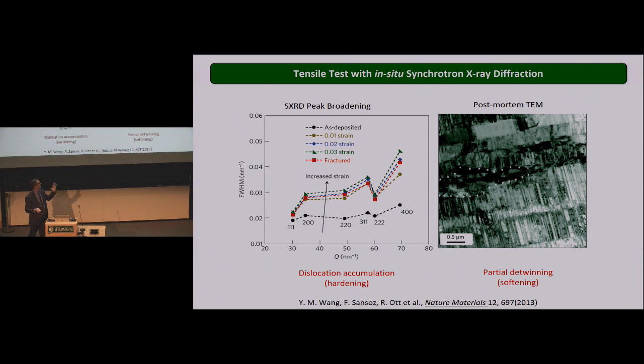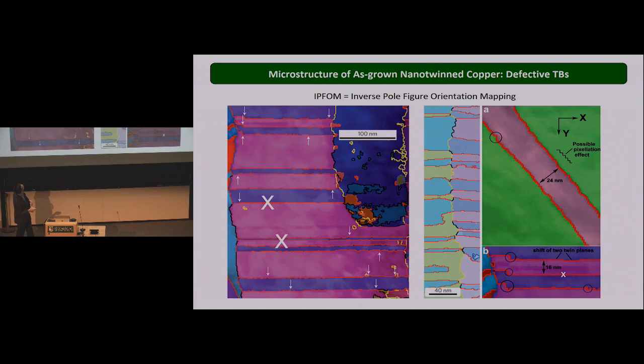So how to solve this problem requires some very special resources. Maurice Wang in particular has access to a new technology that enables you to do crystallographic analysis on a very small, nanoscale. This is called IPFOM, the inverse pole figure orientation mapping inside a high-resolution TEM. It gives you these pictures. It's a cross-section of one of the grains, a nanotwin grain. And the colors show the crystal orientation.